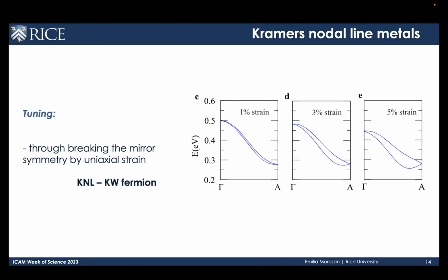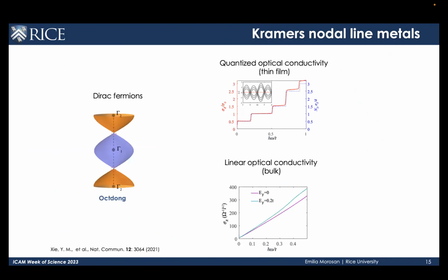The other interesting thing about these Kramers nodal lines is that with some tuning, for example, with strain or breaking the mirror symmetry, you can actually split the degeneracy of the Kramers nodal line, and what you end up with is you go from Kramers nodal line to Kramers-Weyl fermions, which are, like I said, pinned at high symmetry points. So there's great potential for interesting fundamental physics, then also for perhaps functionalities and properties.